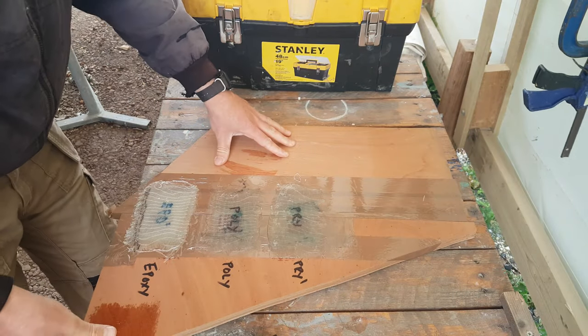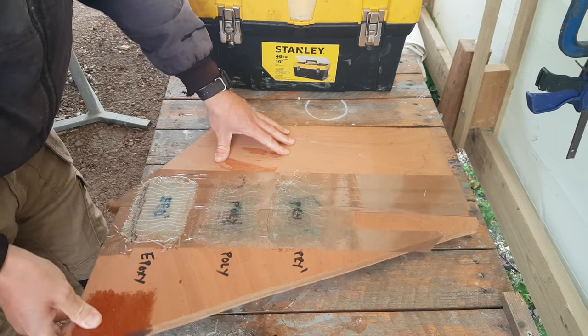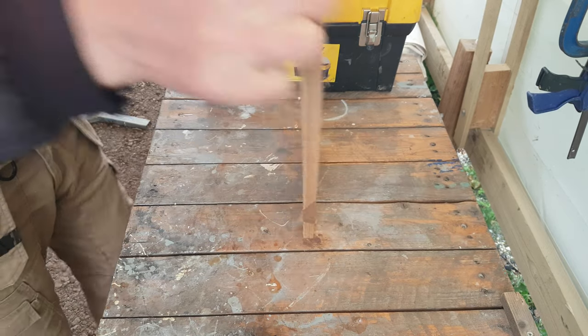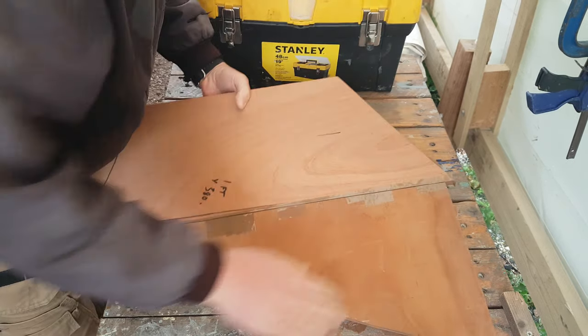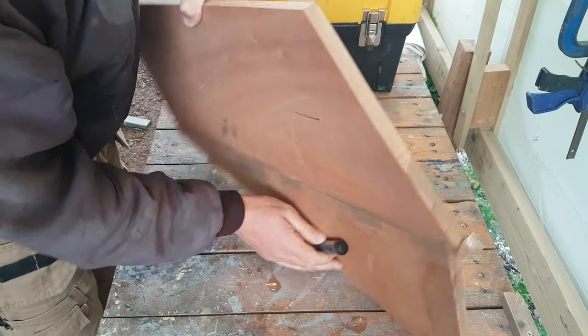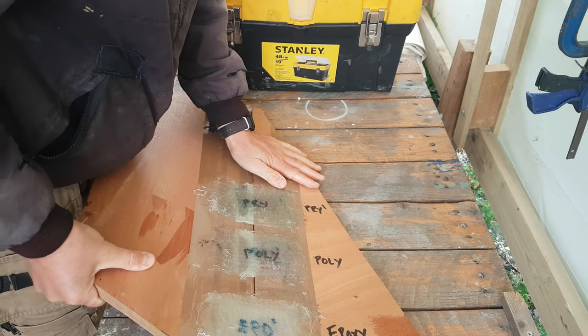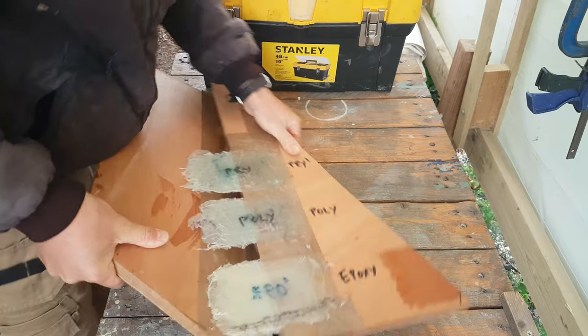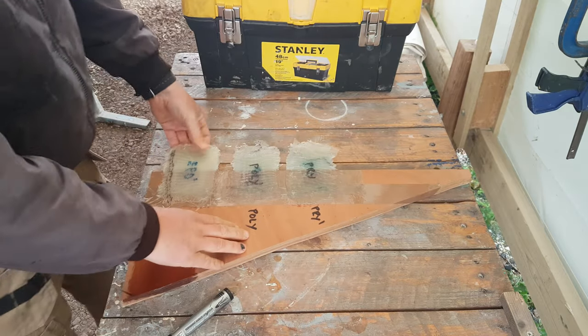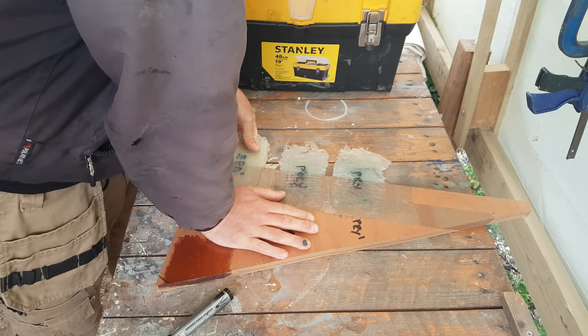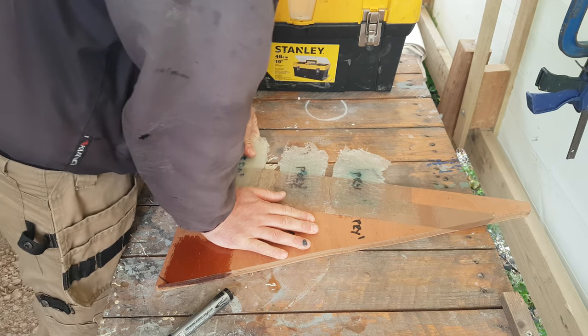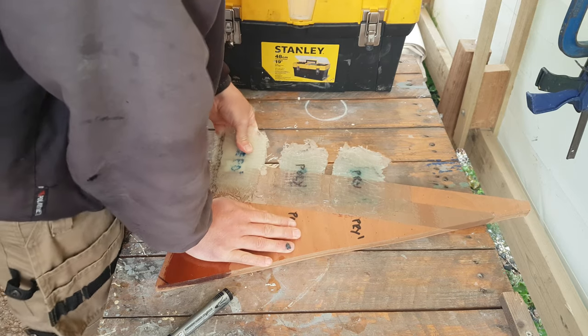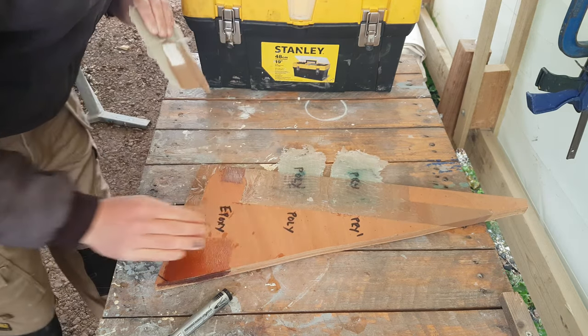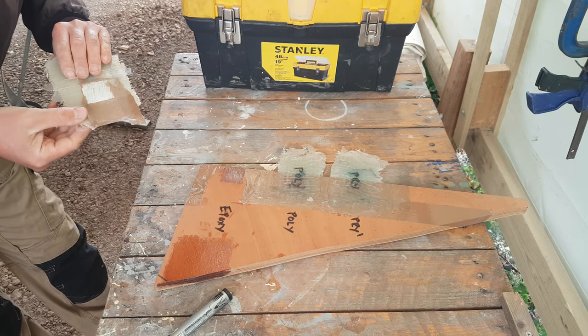Now, after leaving it to cure for a few days, I removed that extra bit of plywood, which was simply there to give me a nice level bed to lay up onto. I then, just using my hands, tried to peel off these tabs. Epoxy first, and on a scale of 1 to 10, it was a good 8. It required a lot of my strength to get that off.